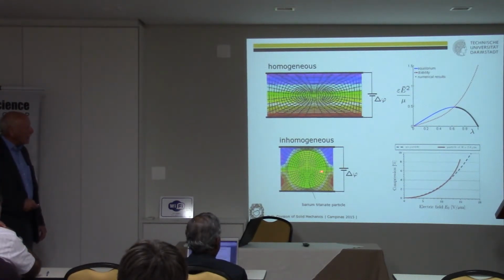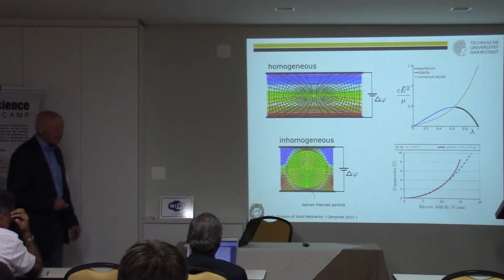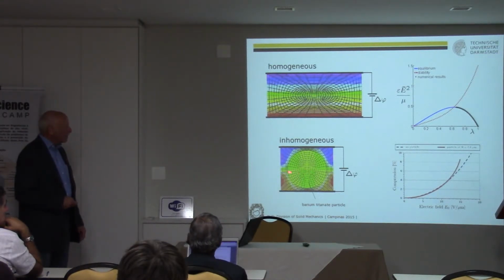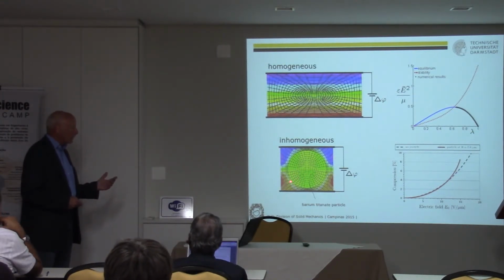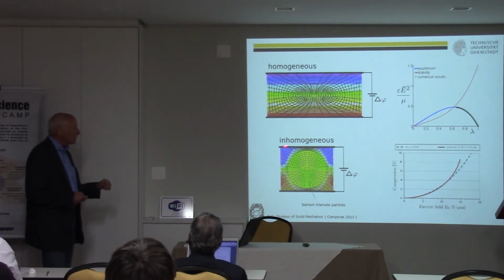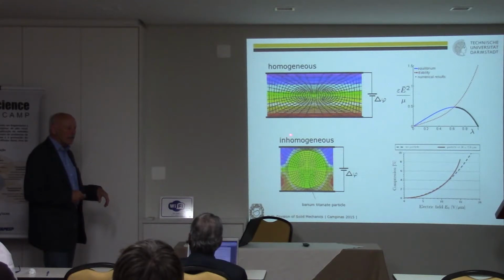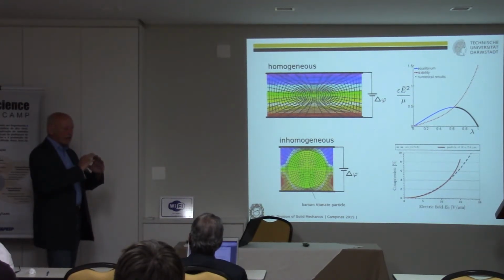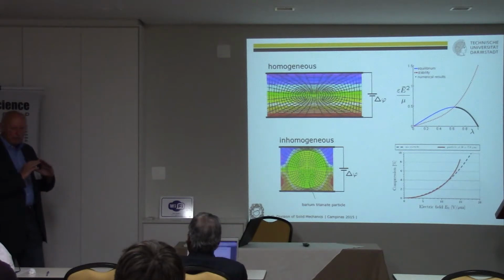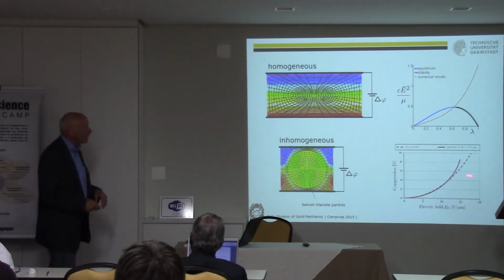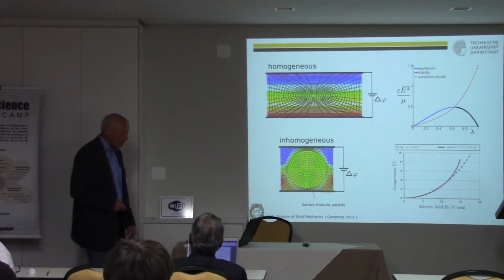And then what we now do, and one student is working on that, this particle, of course, is not the best choice of geometry. There are better choices. You have to think about the size of the particles compared with the thickness of the layer here, and the geometry of the particle. Inclusions, for instance, of elliptical or ellipsoid particles are much better. Then you get this much stronger effect here.